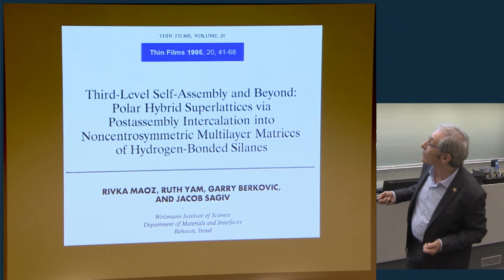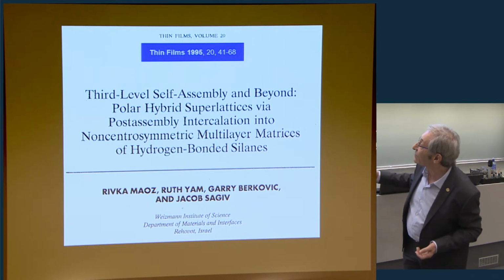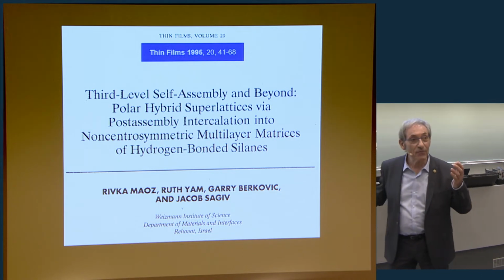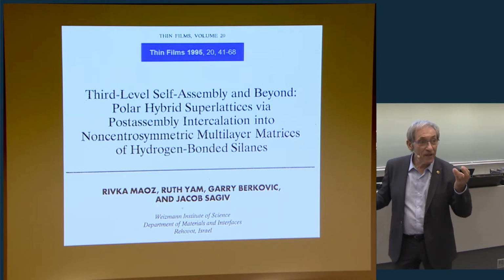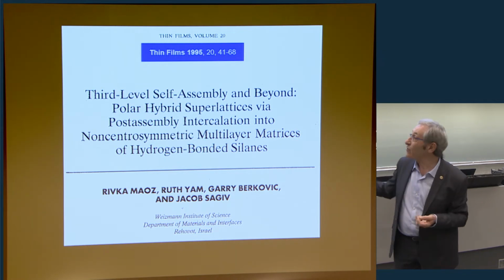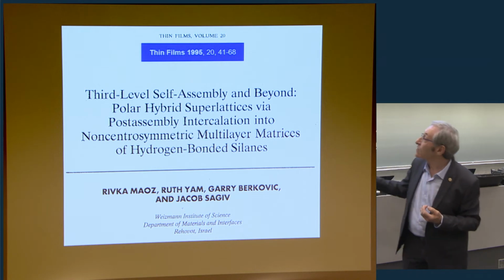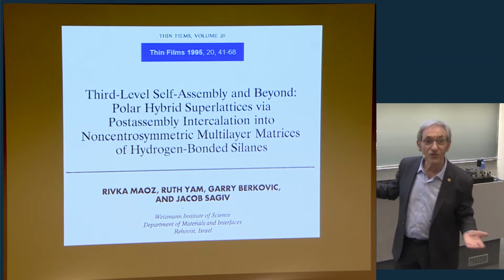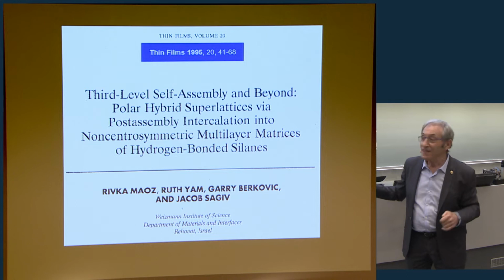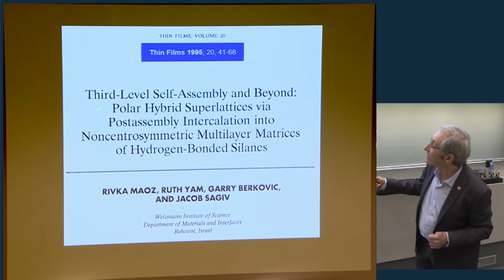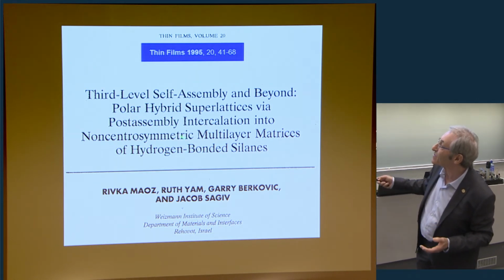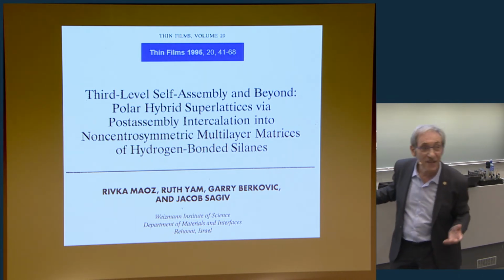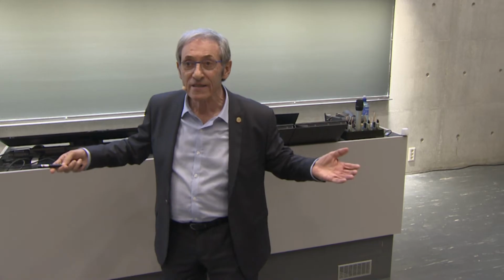And this is the paper published in 1995. You see the title is Third-Level Self-Assembly. What is third layer self-assembly? We assemble a monolayer, first level. We assemble a multilayer, second level, and then we have intercalation in between the layers. So it's third-level self-assembly and beyond, because you can then modify what is inside. And polar hybrid superlattices via post-assembly intercalation through non-centrosymmetric multilayer matrices of hydrogen-bonded silanes. So this opens a lot of possibilities.